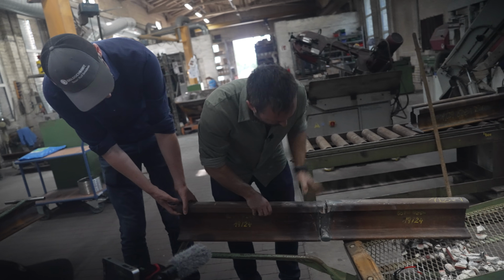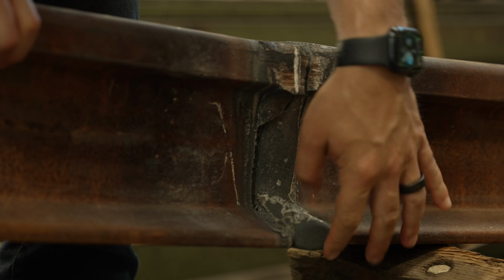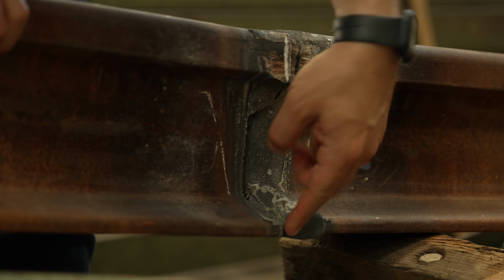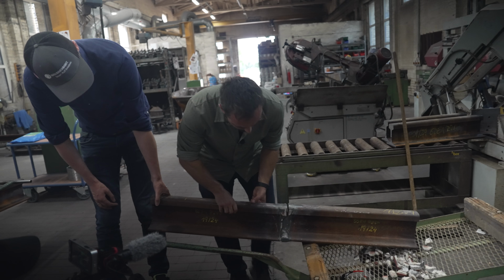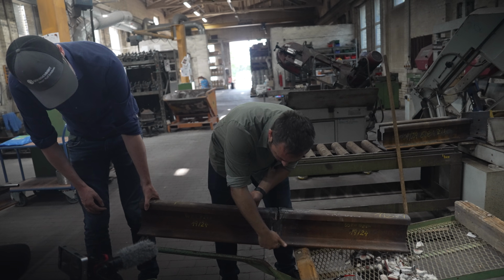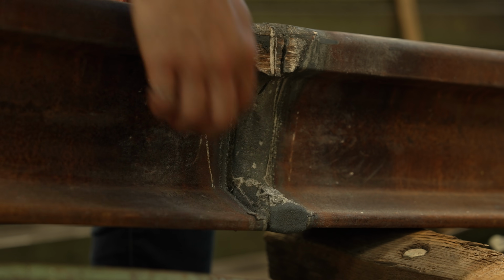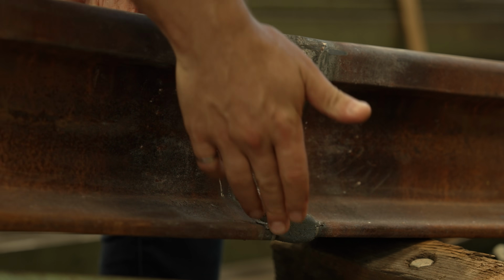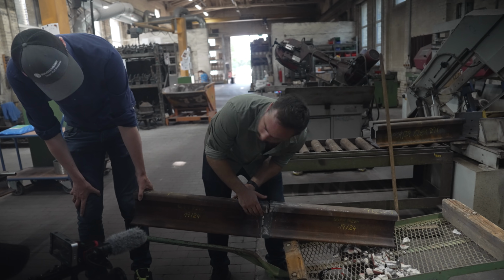Just over 150 tons. So we think the crack propagated from the bottom upwards because it's being pushed down like that. So this is under a lot of tension. Yes. So it breaks under tension down here, rips up this way. And so it doesn't break in the middle of the weld. You're saying this zone beside it, which is a previous rail material that got heated up in the weld, is actually weaker. Yes.